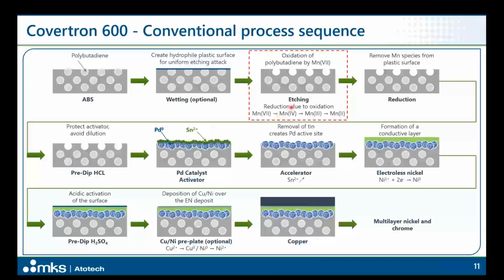The process sequence in detail for a conventional plating on plastic process is shown here. You can see how the Covertron 600 will replace the current sulfuric-chromic etching, and how it is really a drop-in solution, because as mentioned, we don't need any kind of pretreatment here. And of course, we can also work with any kind of pre-plating before the acid copper. So we can work with immersion copper, a copper strike, or a nickel strike.